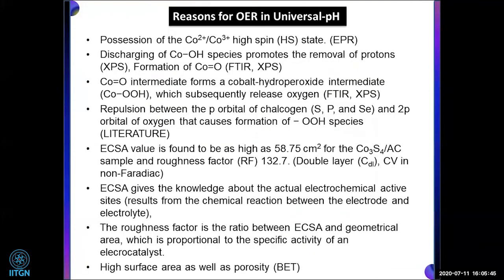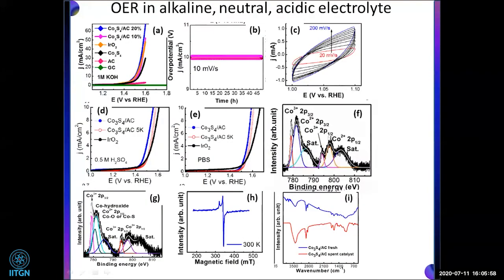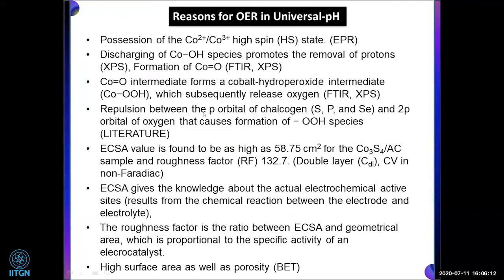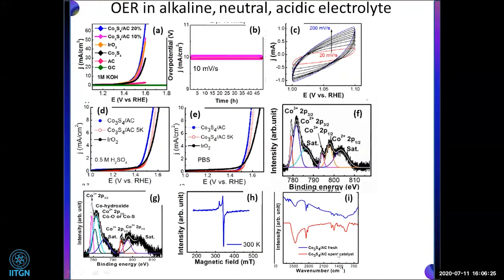The next one is the discharging of this cobalt hydroxyl species, which promotes the removal of protons, and finally we get cobalt OOH species. You can see from here, this is the XPS of the fresh catalyst, and this is the after-stability catalyst. We can see clearly the cobalt hydroxide and CoOOH peaks here, which support our claim. One more thing, the repulsion between the 3p orbital of sulfur, or the 4p if it is a selenide, and the 2p orbital of the oxygen causes formation of OOH. From FTIR, what again we can see here is the formation of OOH species, which is not present in the fresh sample.